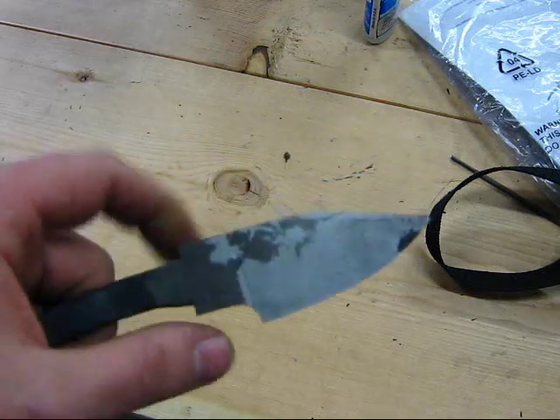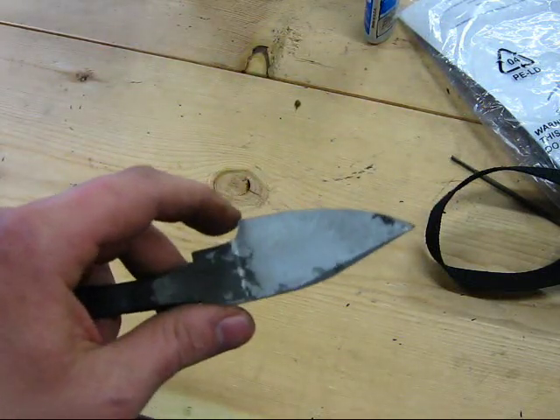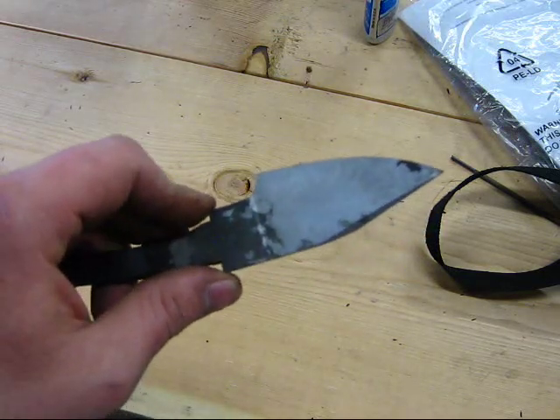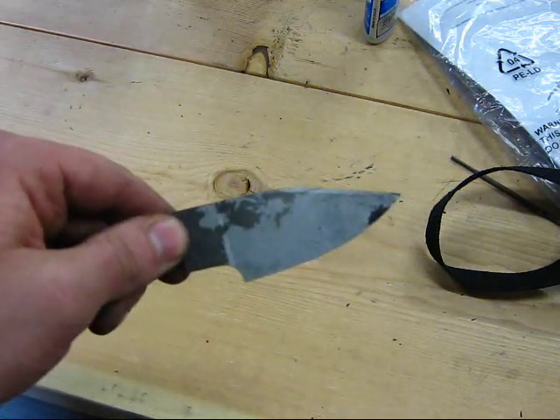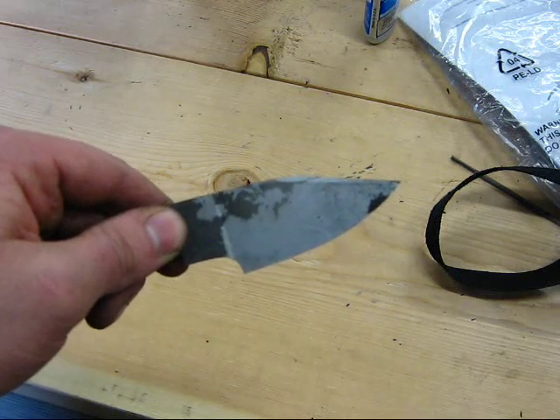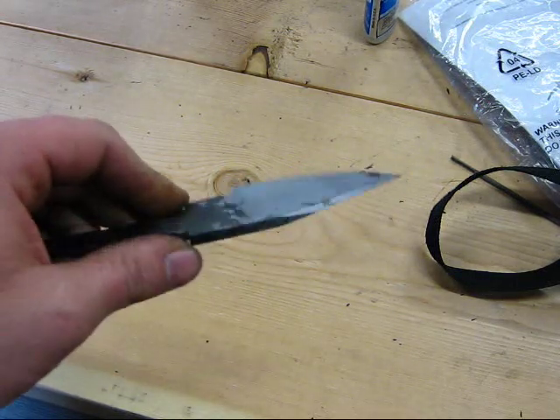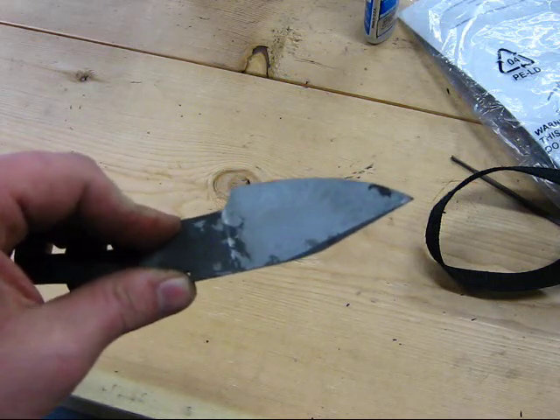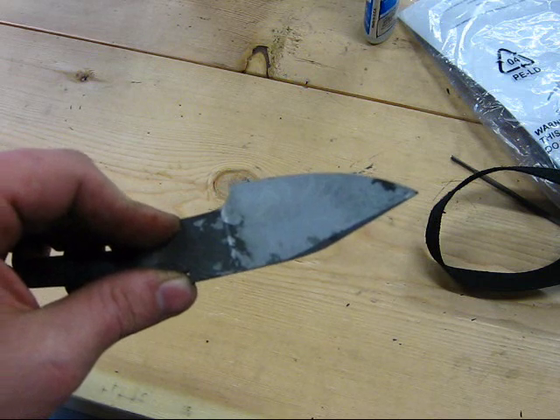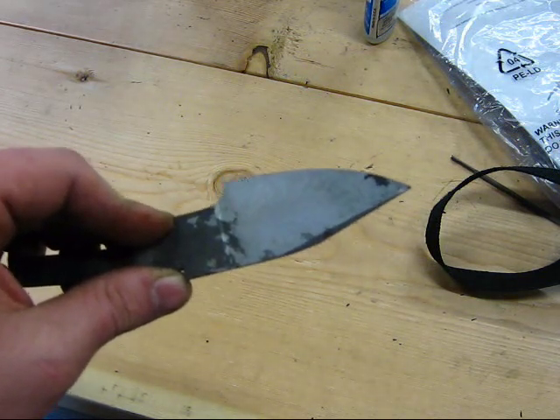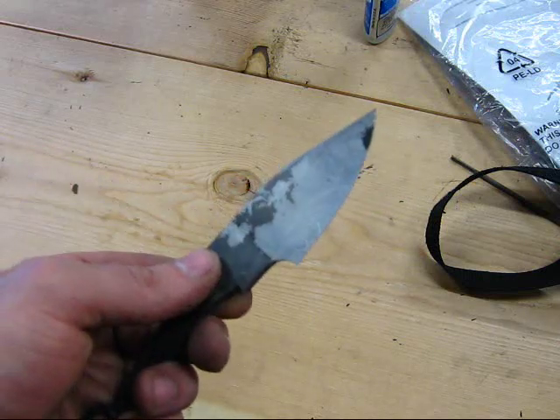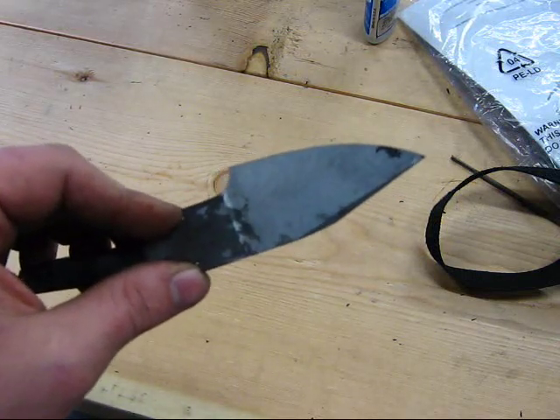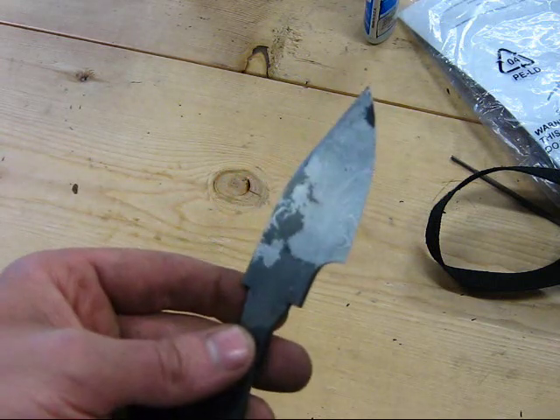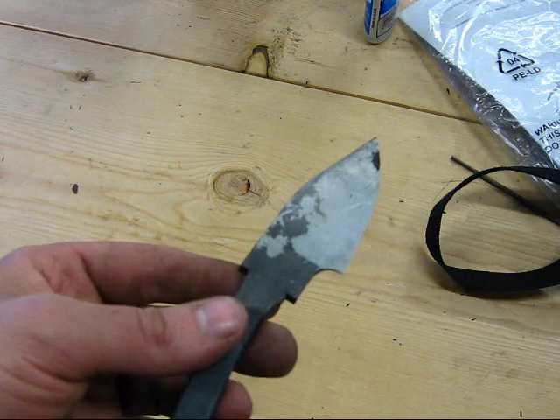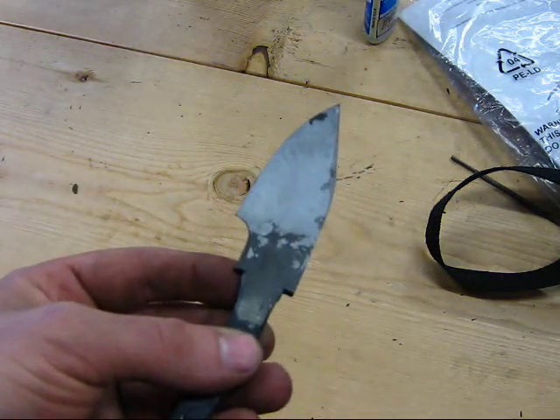Now, tempering, like I said, will remove some of the hardness, but it comes with a trade-off. The ideal heat treatment for a knife is one that will hold a good edge, so it's hard enough to the point where it will hold a good edge, but tough enough and soft enough that you can use it for its intended cutting purpose without the edge chipping out, or without you breaking the tip or cracking the blade or whatever it may be. So different knives have different ideal heat treatments, and each different knife needs to be heat treated according to its intended use.